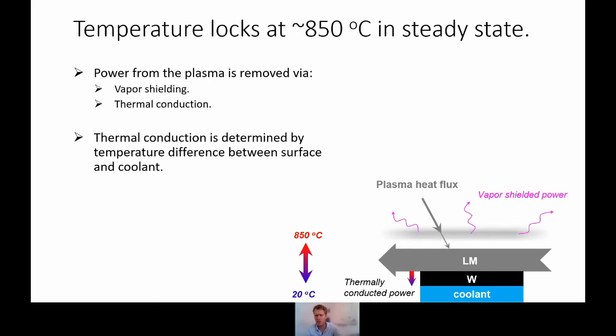And the surface temperature is locked. We find experimentally that it's always locked at 850 degrees. So that means that if this temperature difference is fixed, also the amount of power going to the coolant is fixed. And this is actually great